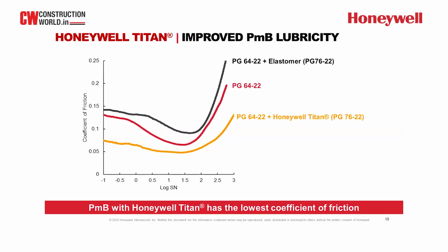In general, when you add some traditional polymer, especially the elastomer, like SBS, into the bitumen to produce PMB, the COF, you can see here, right? So COF will increase. That means the friction when you move the aggregate around during compaction will be high. So that's the reason that, compared to the base bitumen, when you switch to PMB with SBS, it will require higher production temperature and also higher compaction temperature, right? Because of the higher COF.